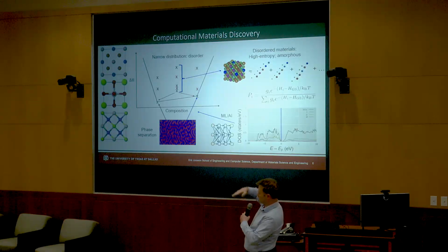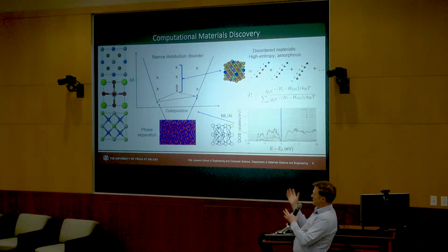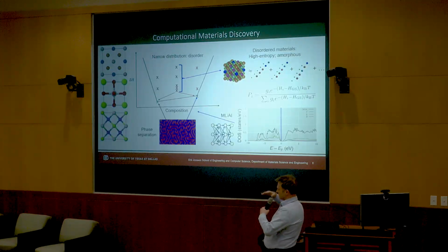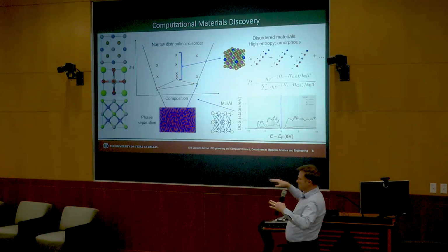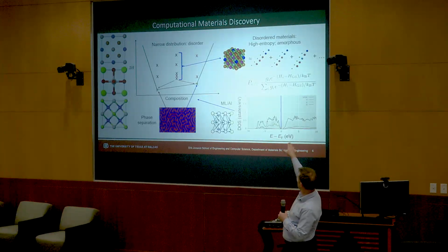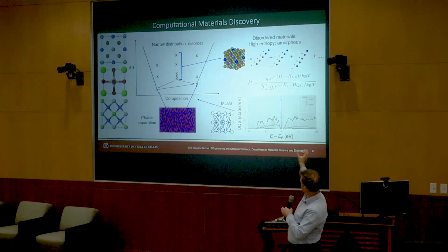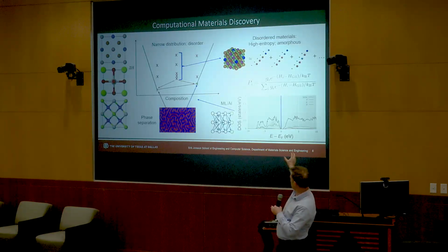But beyond just stable compounds, we can also say something about disordered materials. If you have a wide distribution of energies, then it's clear which structure wants to form. If you have a narrow distribution of energies, then during crystallization these are going to compete against each other, and you're going to get something like an amorphous structure, like a glass. If the structures are similar to each other and a lot of the energies are the same, then you get a disordered structure: a crystal lattice, but occupied randomly, like you have on the right here. Then we can calculate the properties of these disordered materials from a linear combination, a weighted average, of the properties of the components. So we get something like a density of states that we see at the bottom.